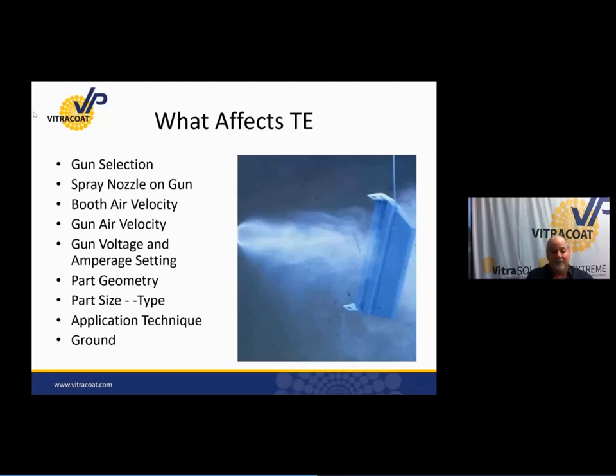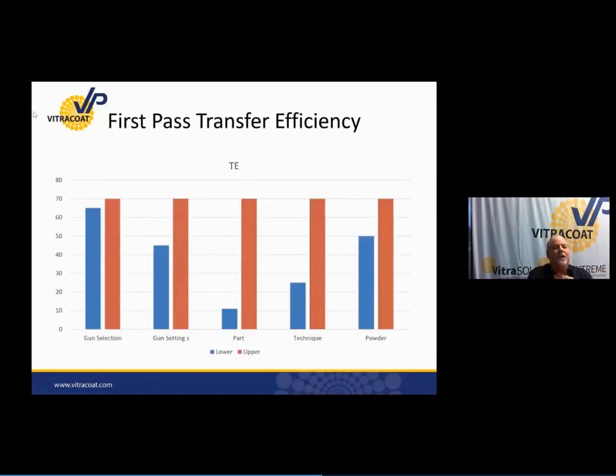The part geometry and the size or type of part are very key in impacting transfer efficiency. Application technique can and will impact transfer efficiency. And the quality of the ground can be a very important factor in transfer efficiency. Let me give you some percentages. We took transfer efficiency up to 70% and then made variables within that application. The gun selection had the least amount of impact on transfer efficiency. The red being the high end, and as we made changes on the left side, different guns, there was only about a 5% difference, 65 to 70%.